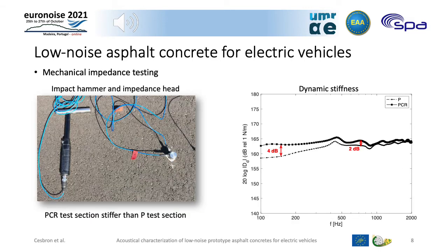The mechanical impedance was also tested on both asphalt concretes. The experimental setup is based on the frequency response function between an impact hammer and an impedance head measuring the direct force and acceleration at the impact spot. On the right hand side of the slide you can see the dynamic stiffness of sections P and PCR in the frequency range between 100 Hz and 2000 Hz. As you can see, the dynamic stiffness is almost constant over this frequency range, thus corresponding to an ideal spring behavior.